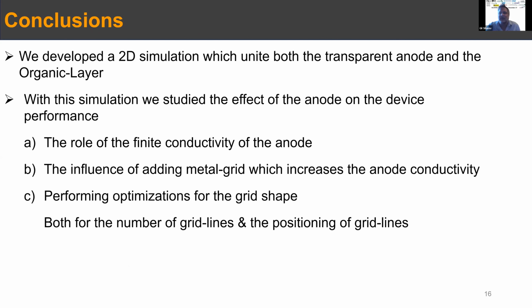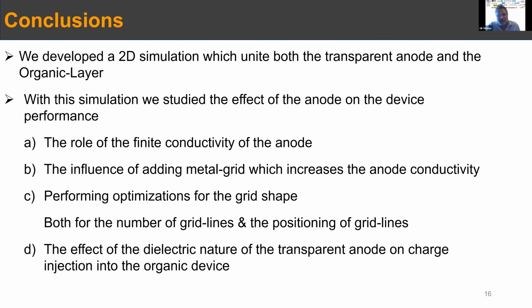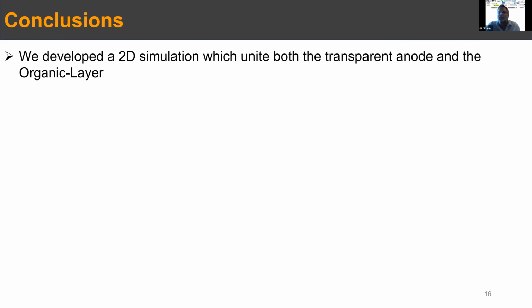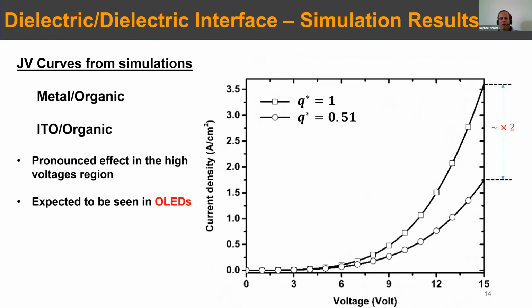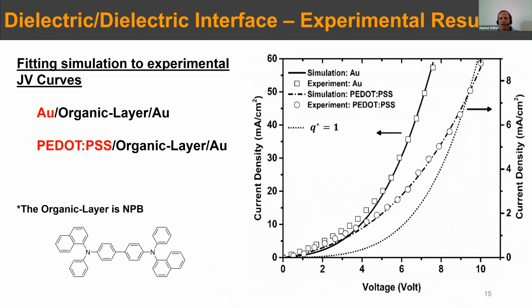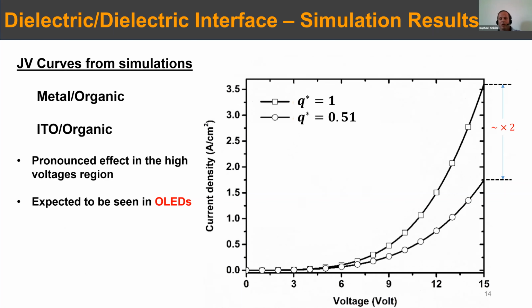So basically the formulation that you did for ITO, this will be also valid for? ITO, yes. We measured it for PEDOT:PSS. So it can be for any kind of a dielectric electrode. But not only the electrode, also the active material. It could be silicon. You still have the same problem? Yes. You will have something different, yes, obviously. You can take it even to extreme, just put water. You will get Q star, which is negative. I see. That's really extreme.